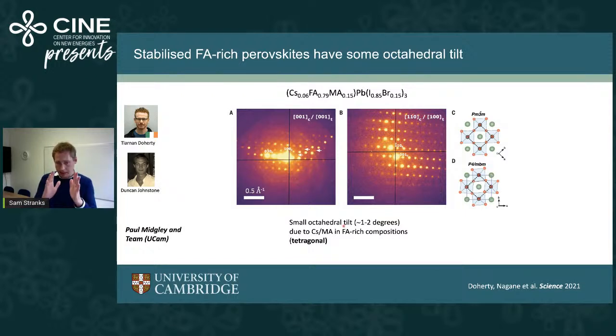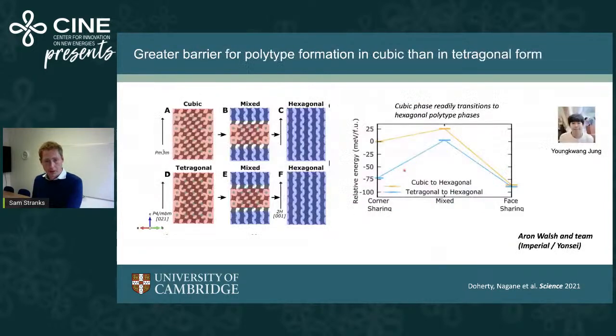And so what that means is that these octahedra are slightly tilted away from cubic, only by a few degrees, 1 to 2 degrees. We believe this is from the cesium and methylammonium that is there with the formamidinium. So these extra ions, these alloys, tilt them very slightly.